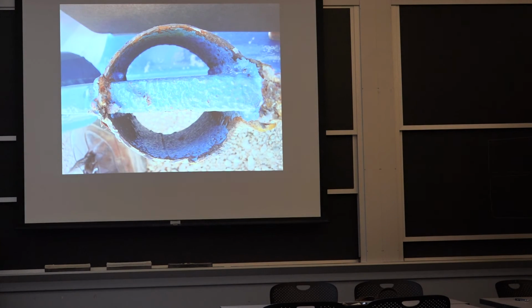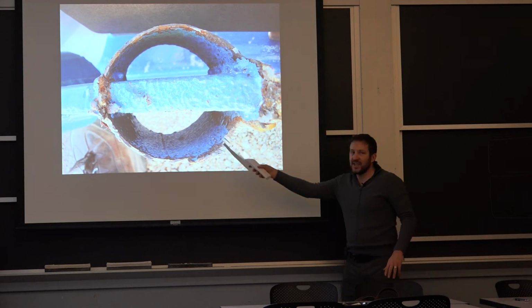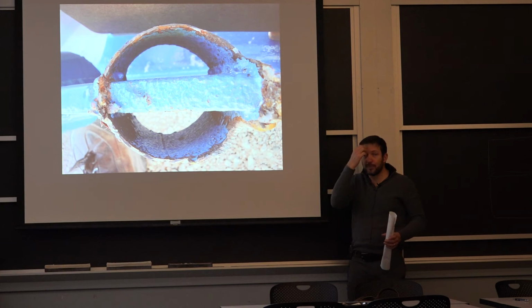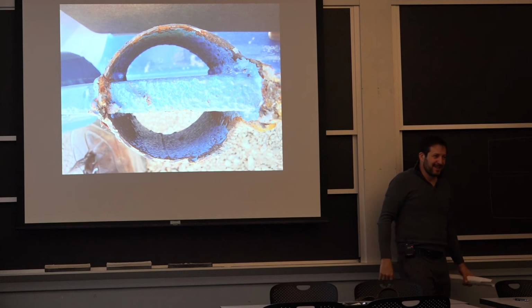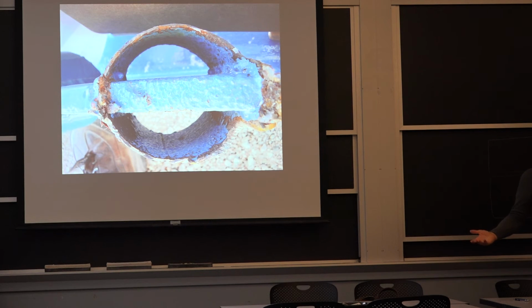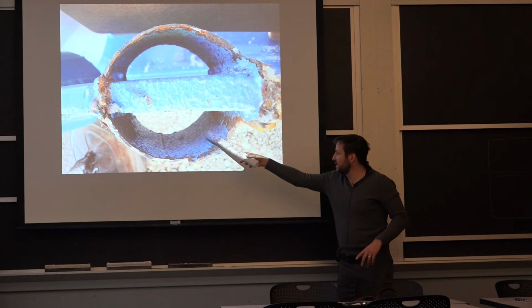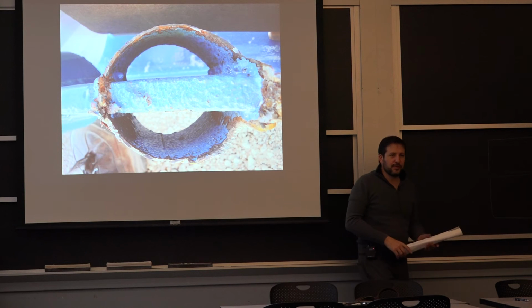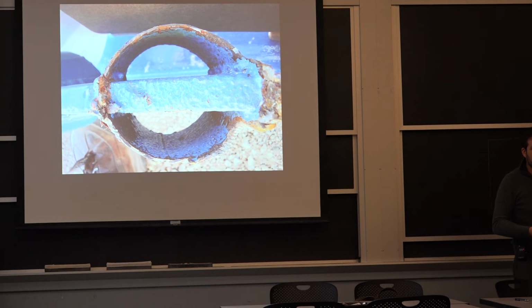It wasn't the only issue. When they refurbished the crane, you can see some corrosion on the inside of the tube that was painted after the fact. So this is reality. I'm not making anything up. So it was heavily pitted. You see the roughness, and you see the paint over the roughness. So you knew you had a significant thickness reduction. And as any atmospheric corrosion goes, that thickness was not the same everywhere. So it does add to essentially make this connection really not as good as it was in the first place.